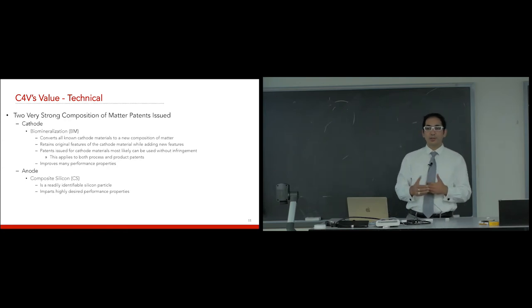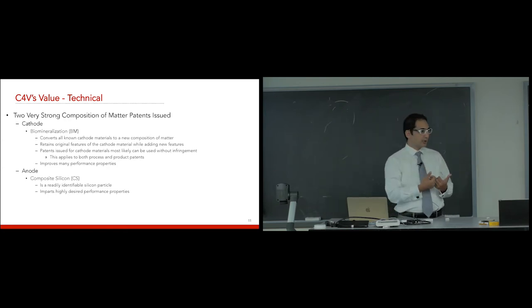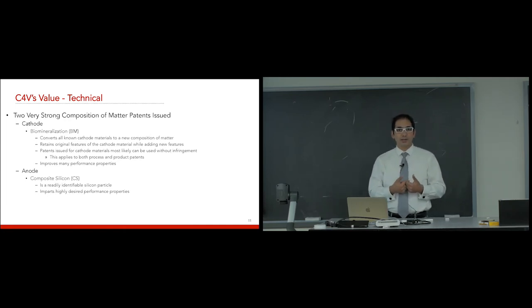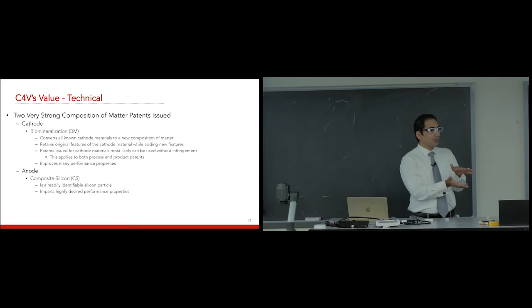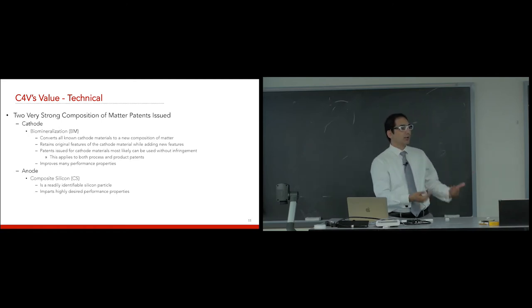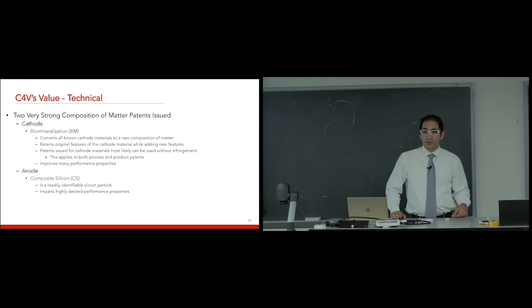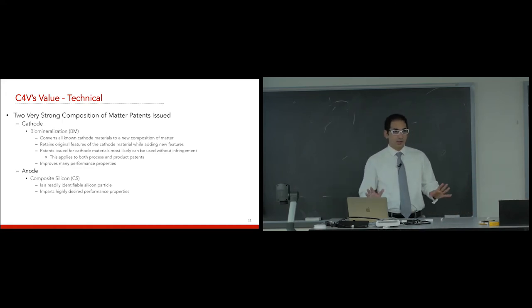And that's one example. Also, when you charge your battery to higher voltages, that also puts a lot of strain on your crystal system. So if there is a stability or pillaring agent that can protect against that breakage, that will also give you a higher voltage advantage, which means higher energy density in some cases. The most popular material used as a cathode in our iPhones, everybody uses it, and it dies by the time you hit your bed. So everybody is frustrated with the energy storage capacity of our smart systems. But despite it being one of the oldest materials used, called lithium cobalt oxide, in our batteries, we are only able to extract 50% of the capacity that it can deliver. So theoretically, it can give you a 2-day lifetime without any material change, just by taking it to higher voltage.